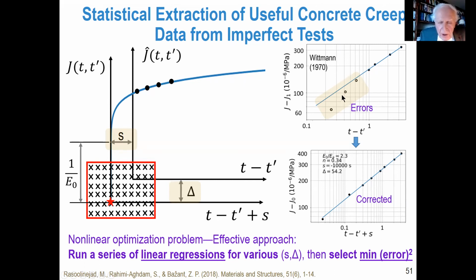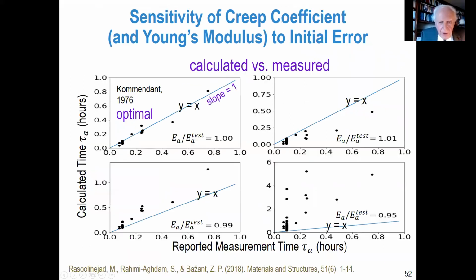Correcting the data. I show one of many data sets which we corrected, and that will be published on the website of this Northwestern University database. These are classical data of Wittmann, who measured on cement paste. That was considered very good because these curves fit a very nicely smooth line. But it does not fit the power law, so there must have been an error in the initial setup. And when we correct this, we get a perfect straight line, a perfect law. So I think that's one of many validations which we have by minimizing this error of the regressions.